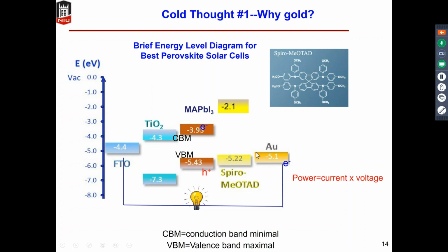The electron transports from the higher level of the electrode to the lower level of the valence band of MAPbI3, and that energy will have to be converted to heat. So you don't want a lot of electron potential energy to be converted to heat. So you want the Fermi level of the metal to be as close to the VBM of the MAPbI3. That's why, because of the value of this VBM of MAPbI3, you have to find some large work function metals.